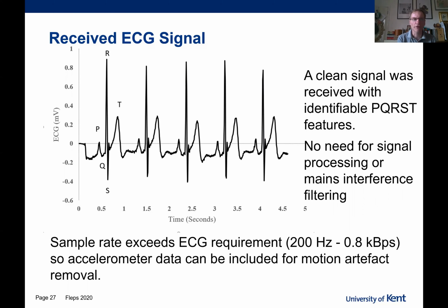The features that I observed in ECG, the PQRST features, are readily observable. The signal-to-noise ratio is very good. And in fact, there was no need for any processing on this signal. This is as received, so there was no averaging, no smoothing, and no need to remove mains interference, 50 or 60 hertz, which often requires notch filtering. The sample rate is higher than is needed as well. We required a 200 hertz sample rate, which is about 0.8 of a kilobyte per second, and we have around 5 kilobytes available.